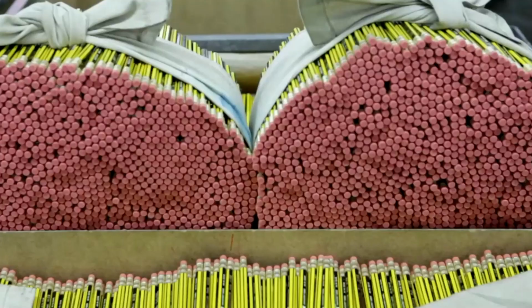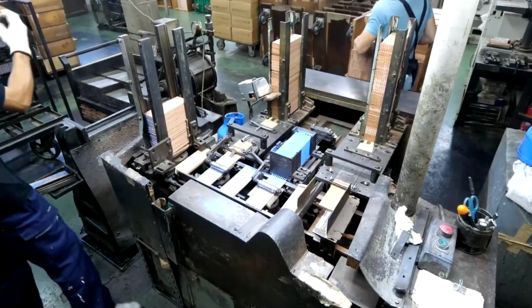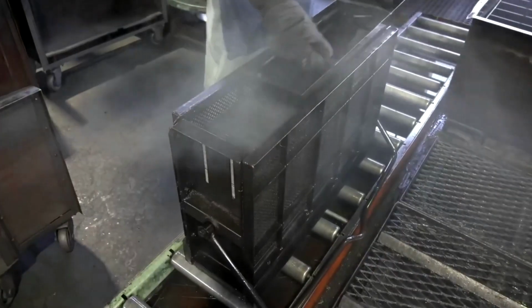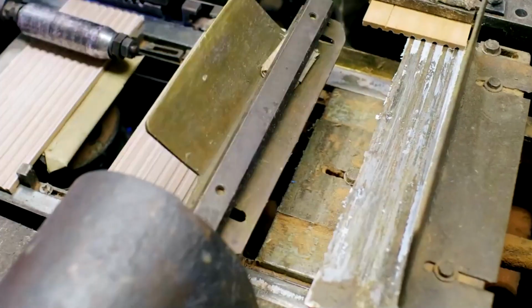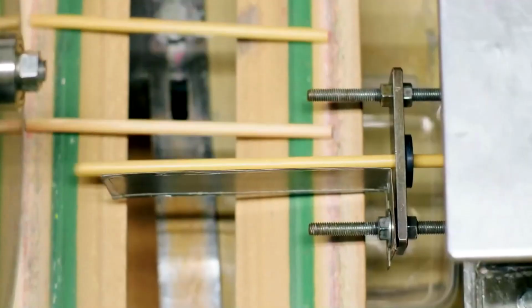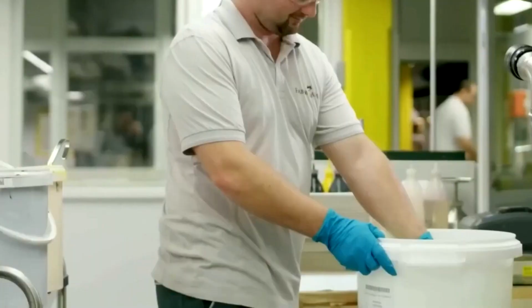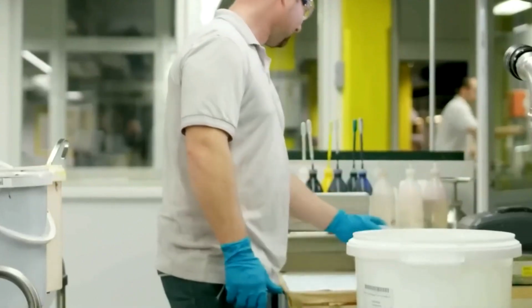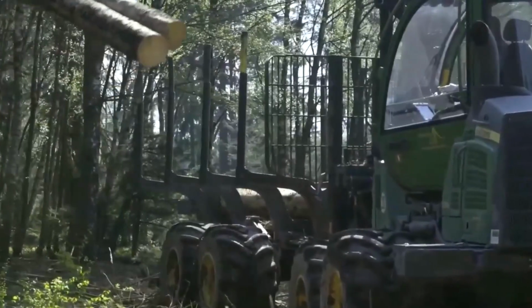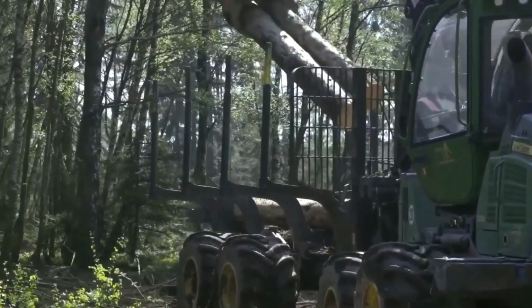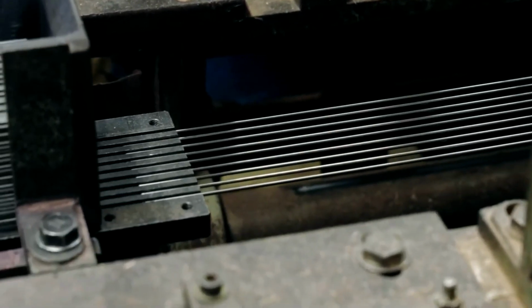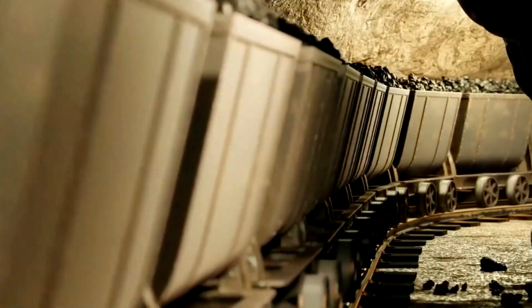Why is the ratio between these two materials monitored so strictly? It looks outwardly simple to mix these powders, but in reality, this balance defines the hardness grade of the pencil. A higher concentration of clay results in a harder, lighter core known as an H grade, while more graphite produces the soft, dark stroke of a B grade. Industrial mixers knead the mixture until it reaches a perfectly uniform consistency.